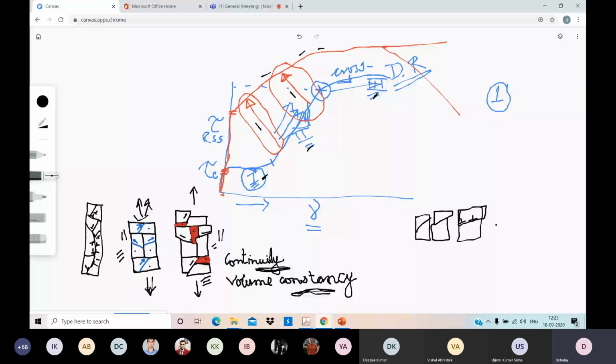So it's not necessary that dislocations only end up at the surface of the single crystal. It may remain in the middle. Any movement of a dislocation will give you some amount of slip. It may be one Burgers vector of slip, it may be less. So the dislocations that cause you slip are the statistically stored dislocations.